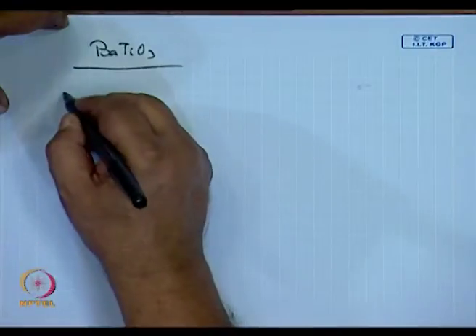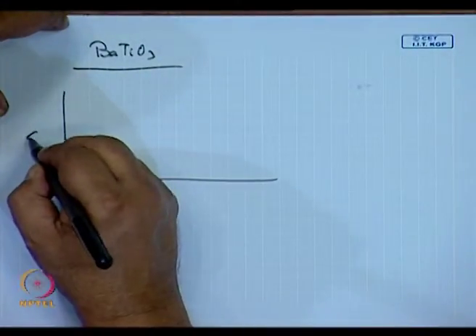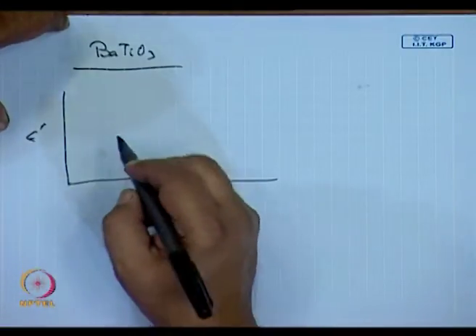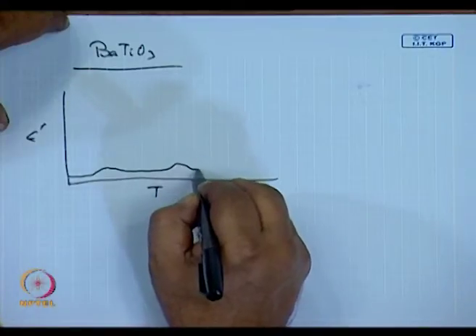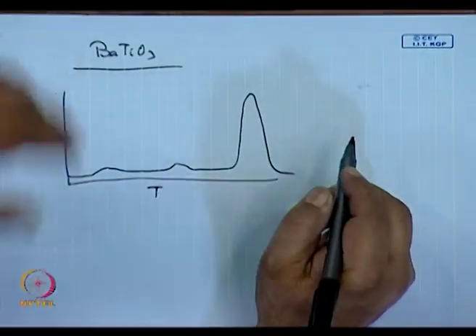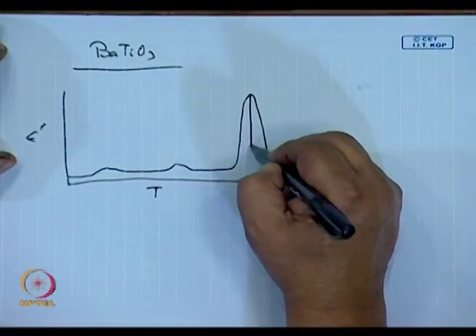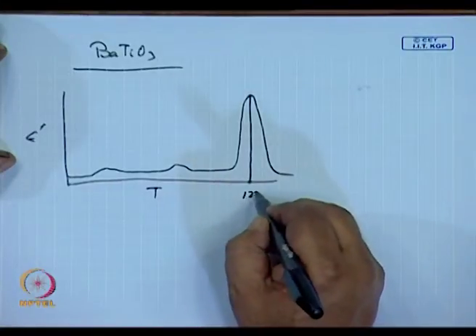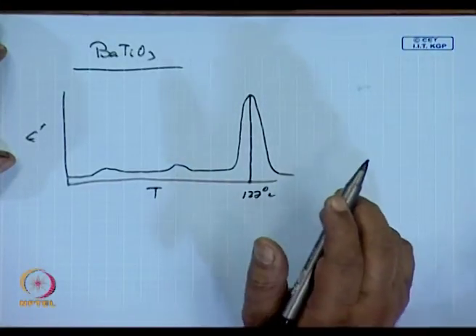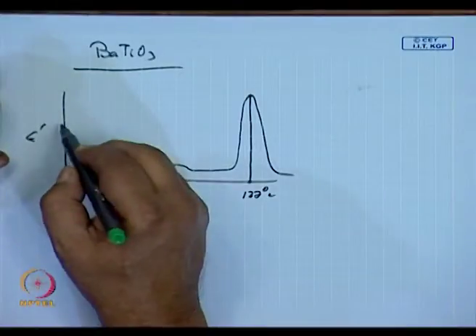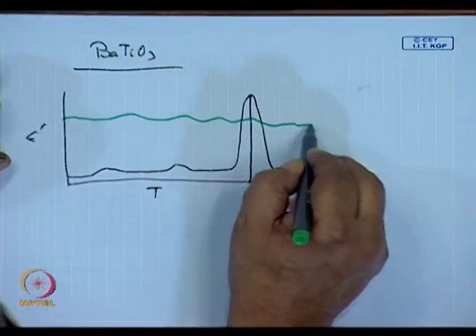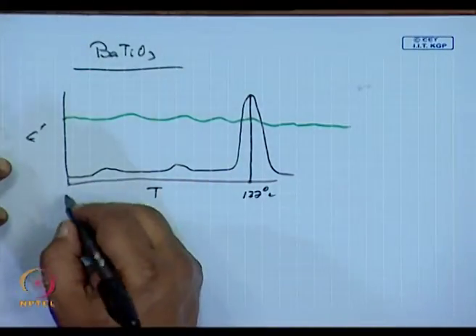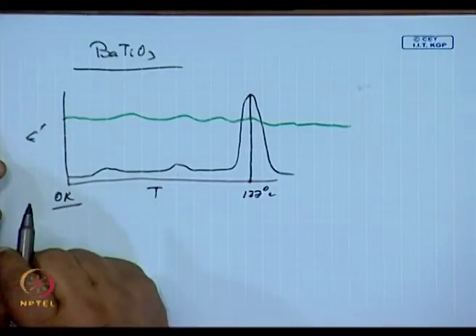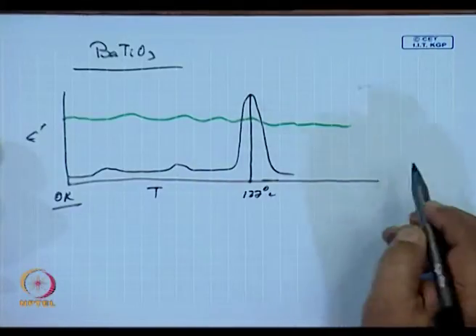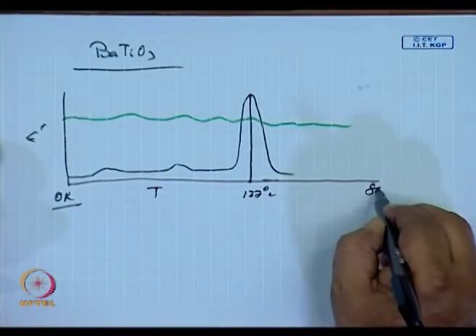If I am looking at the dielectric constant versus temperature, the so called very high dielectric constant is there only at this Curie temperature, which is 127 degrees centigrade. Now, no device will operate in this place. What we really need is a reasonably flat response across a temperature from near 0 K, because you are in space, to a temperature somewhere near 800 K.